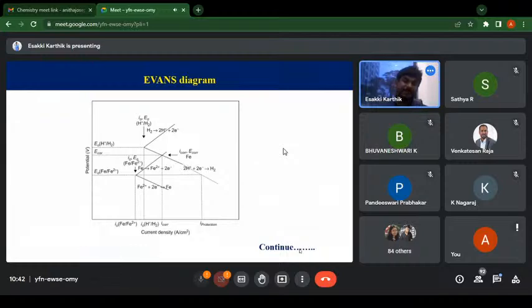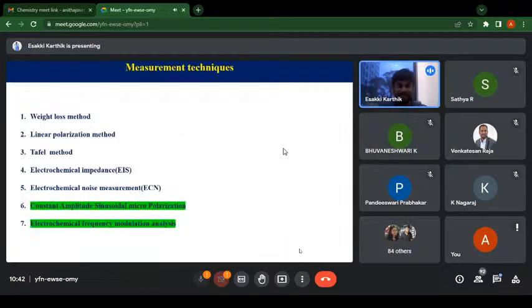The Evans diagram is based on every material's electrochemical potential, and they constructed it theoretically based on the current density. They measured, suppose for Fe2 plus, the current at equilibrium, and if the equilibrium gives this much current density, then they extrapolated. During the extrapolation, they found E corrosion, I corrosion, everything. Then based on that, they calculated the corrosion rate. That we will see in the next slide. This is the theoretical picture. Theoretically they plotted, and experimentally this same Evans diagram we can get through the Tafel plot. That also we can see. These are all the basic methods. That is just the introduction I have given.